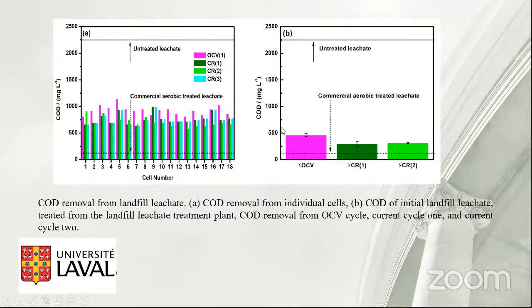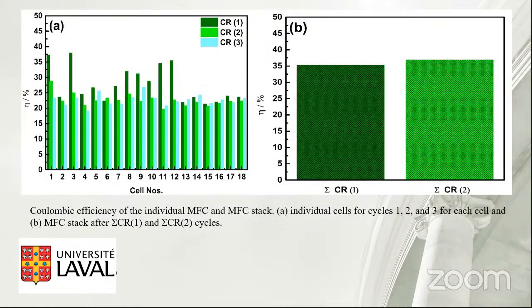That was quite fascinating. So this is about the treatment, because the landfill leachate was highly toxic, but these particular microorganisms can even consume that kind of toxic leachate. And this is the Coulombic efficiency of the system. This graph is from an individual cell, but if you focus on the overall cell, the Coulombic efficiency was 35%, and it was relatively less because we had only small cathodes all over the site. So that was the reason. We consider this in further development.